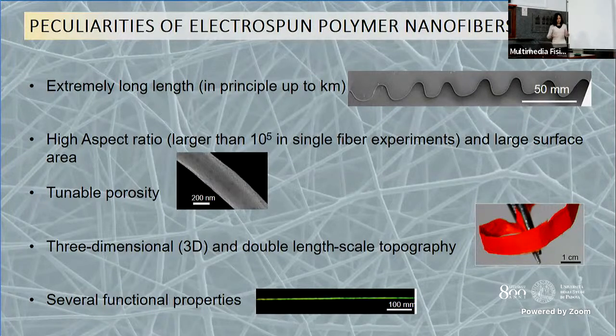Nanofibers, because of their shape and because of the conformation of the chain inside the nanofiber induced by the process used, have some peculiarities that make them very interesting for several applications. Here I report some of them. First of all, they are characterized by an extremely long length. In principle, if we have one jet and you spin for a long time, more than 1 hour, you can get fibers longer than kilometers. And remember that the diameters can be well below 100 nanometers. So they are characterized by high aspect ratio. And high aspect ratio means large surface area.